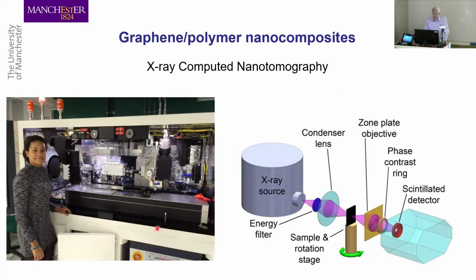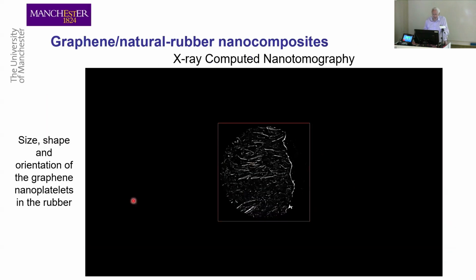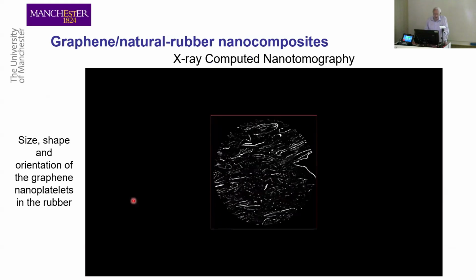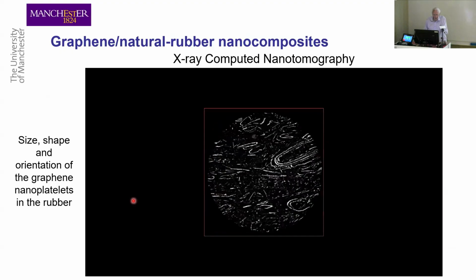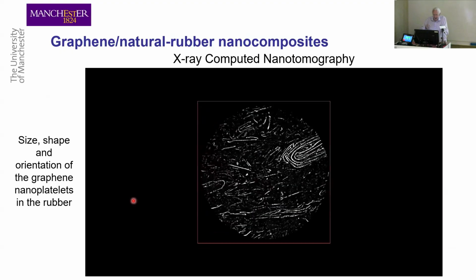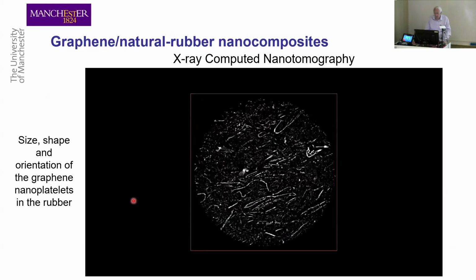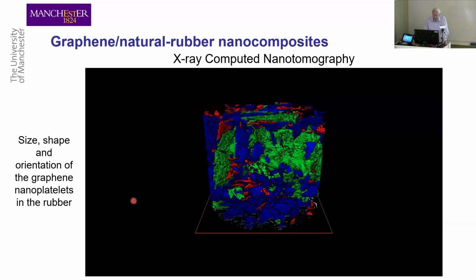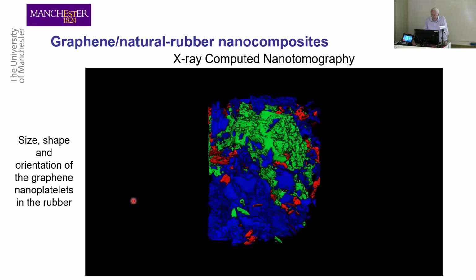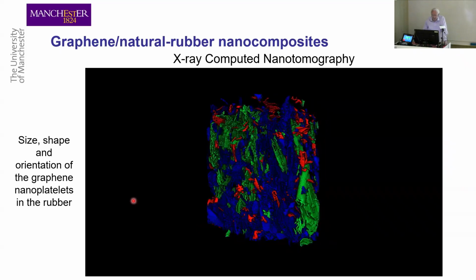And we've looked at graphene polymer nanocomposites. We've tended to use another technique for analyzing the material, which is X-ray computed nanotomography. This is where you have an X-ray source. It's like radiography, but you do it at the nanoscale, and you can do it in the synchrotron as well, as we'll see later. And I've got a whole facility with these machines, and it turns out it's very good at looking at graphene nanocomposites. This is graphene in natural rubber. These are graphene nanoplatelets, which are dispersed in natural rubber. And this is a scan through using our tomography. And you can see it's artificially colored of different orientations and different shapes. And it shows how you can actually see the individual flakes in the material.